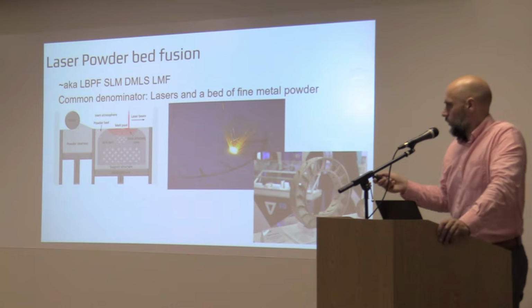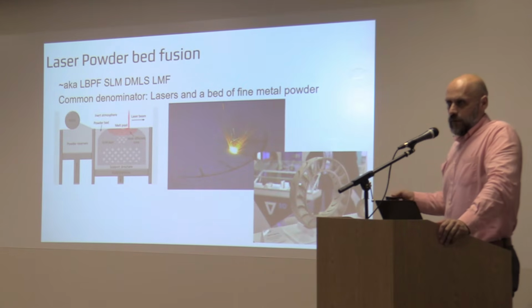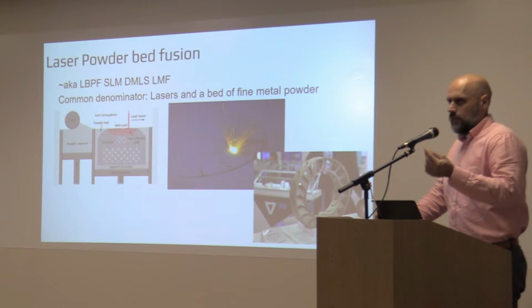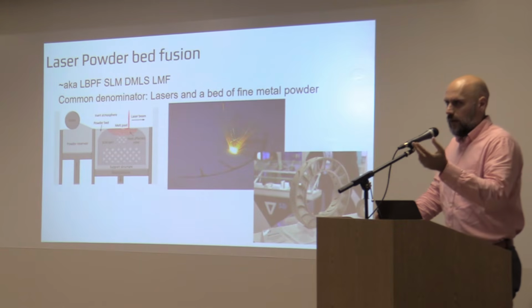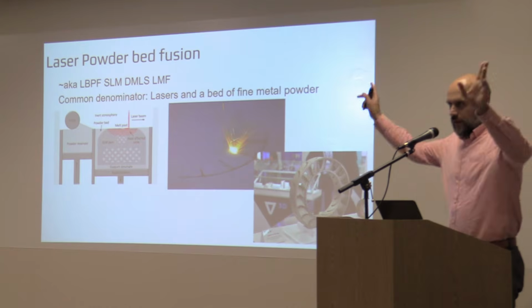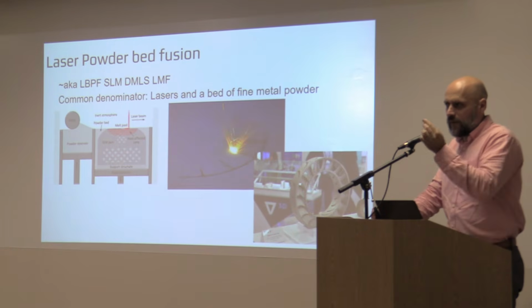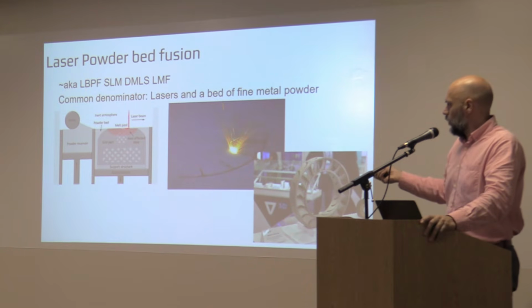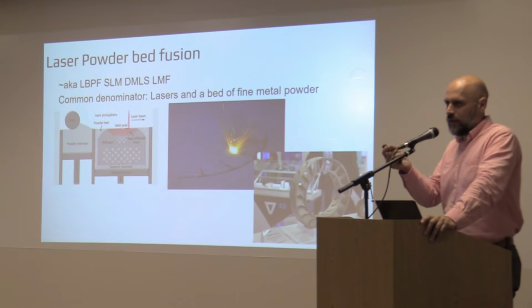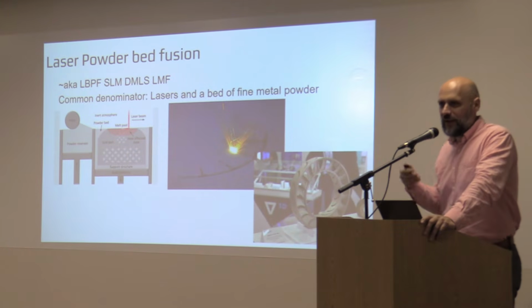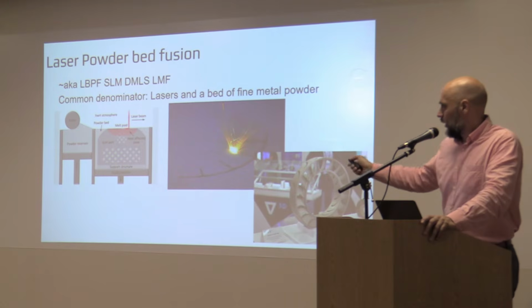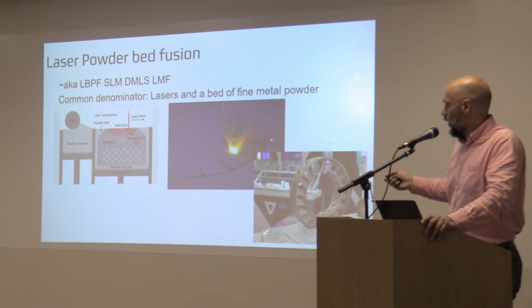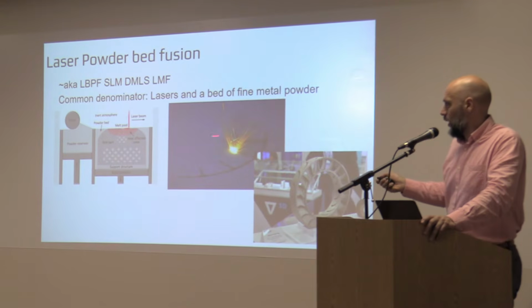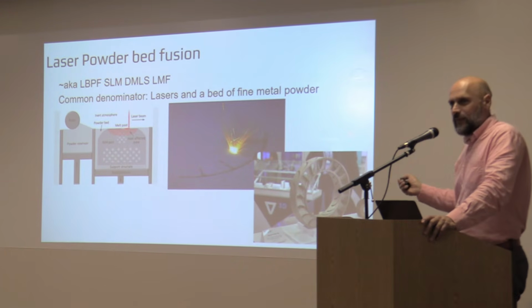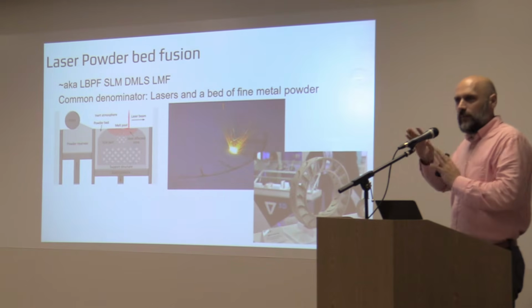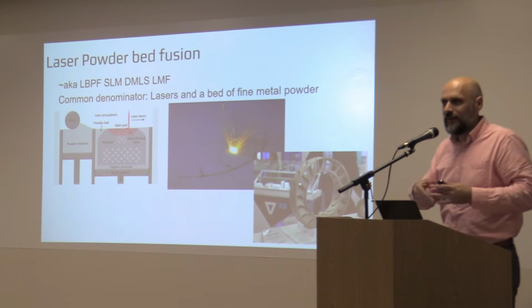And directionally is important because you see all the stuff that is flying out here. This is called spatter. So the laser is so strong that in some areas you make small plasma clusters. That plasma is very violent and starts shooting things left and right. Kind of like weld spatter, but on a very, very fine scale. You don't want that to land on top of your metal. That's going to create a discontinuity because it won't melt nicely. It will create a little porosity, a little void. So you always try to weld from, let's say, right to left, and the gas blows from left to right, against it. So all the spatter goes in areas that you have already welded.